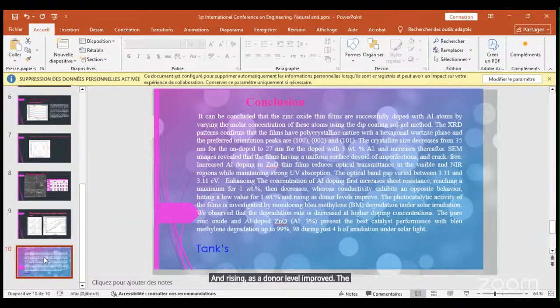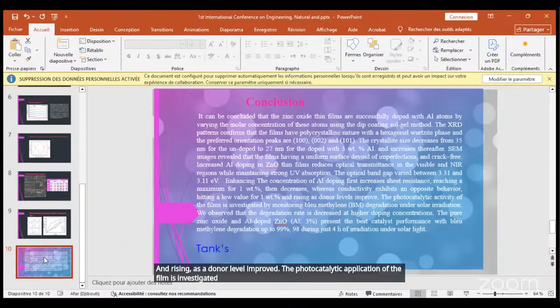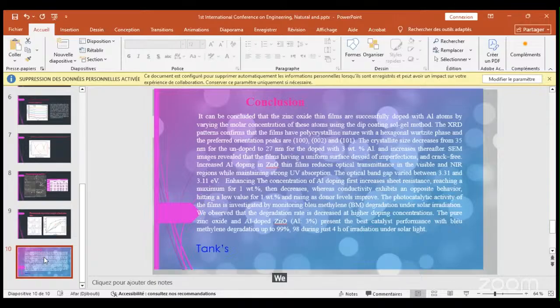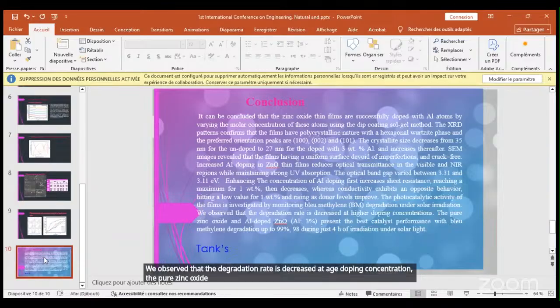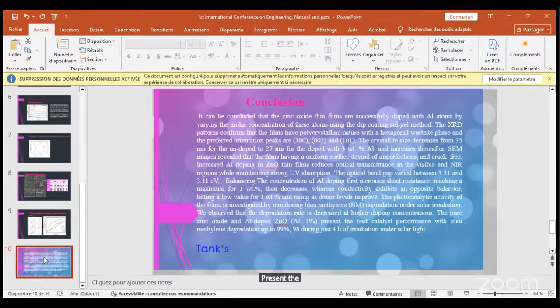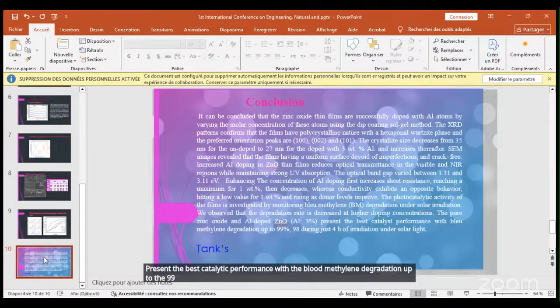The photocatalytic application of the films was investigated by monitoring methylene blue degradation under solar irradiation. We observe that the degradation rate decreases at high doping concentration. The pure zinc oxide and the aluminum-doped zinc oxide at 3% present the best catalytic performance, with methylene blue degradation up to 99%, degrading in just 4 hours of irradiation under solar light. Thanks.